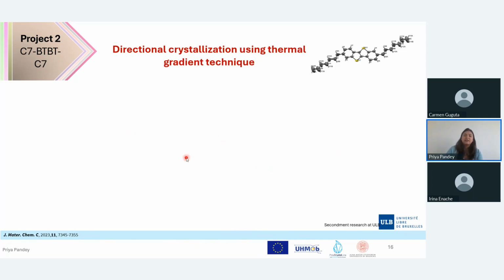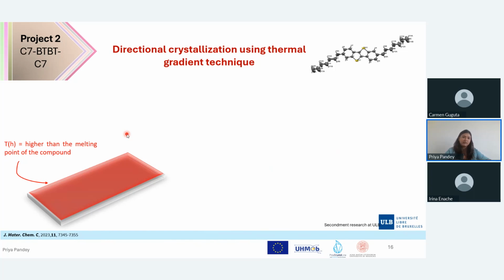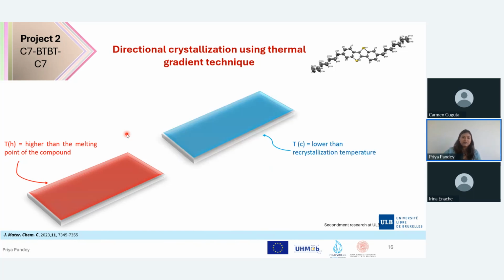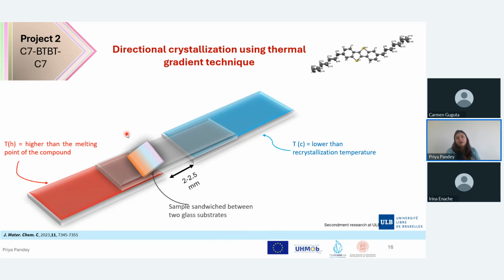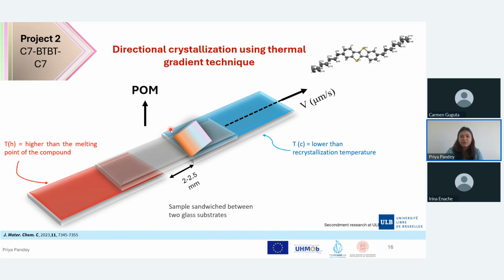So moving towards making the thin films, after trying the conventional methods of making the films, I moved to ULB for a few months to explore the non-equilibrium technique, which is thermal gradient. In this technique, we have two stages, and one stage is called the hot stage, which is set at a temperature higher than the melting point of the compound. Then there is another stage that is set at a temperature lower than the crystallization temperature of the compound that we know from the DSC, right? Both these stages are separated by a gap. We put a glass slide on the top, and we put our material sandwiched between two glass cover slips, and then we melt it on the hot stage. After that, we can give a velocity that we want, and then pull the material from the hot stage to the cold stage, and we can follow the directional crystallization using polarized optical microscopy in situ.